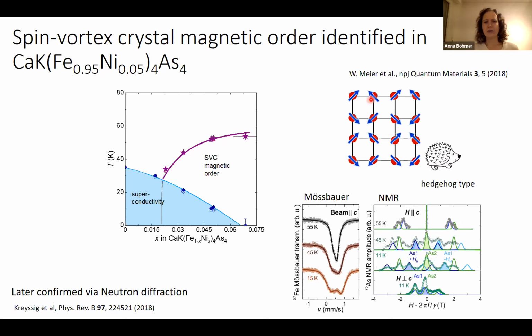In the iron plane, magnetic moments form this non-collinear pattern. And when you go around an iron plaquette, the orientation winds. So that's where this vorticity comes from and the name. And there's actually two types. And this one with some all-in, all-out structure was where we named it hedgehog type, some visual. This was also later confirmed by neutron diffraction. So now we have a variety of magnetic orders in the iron-based compounds.